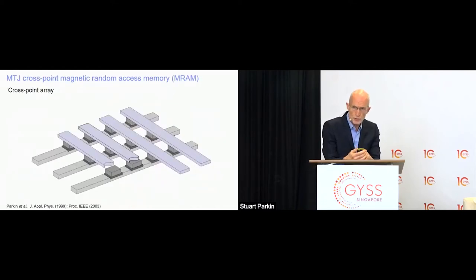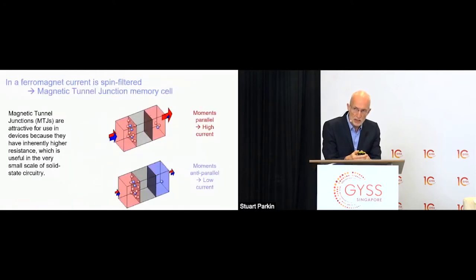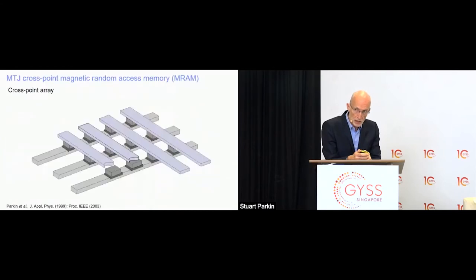But they also could form another type of memory, and this again is the proposal that I and some colleagues made in 1995, that we could use that same tunneling junction as a non-volatile element. The information is simply stored as the direction of magnetic moment. If it's red direction on the right, or if it's blue, one corresponds to a zero, another corresponds to a one, and we can measure the state as a non-volatile state simply by the magnitude of the current that is passed through the device. If it's a large current, then it's a red. If it's small current, it's blue. And we can do that very quickly on the scale of 1 nanosecond for typical devices.